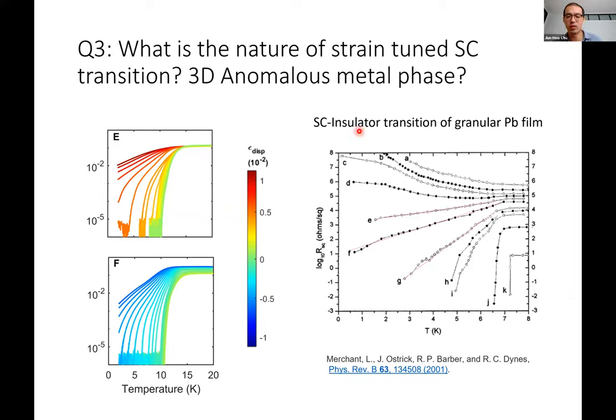two-dimensional systems. This is work done by Bob Dynes on a granular lead film, where they have some lead islands and then repeatedly deposit some silver films to provide conduction between, and Josephson coupling between, the lead islands. So the whole system goes from insulator and then gradually eventually becomes superconductor when there's enough coverage of the silver film around the lead islands.